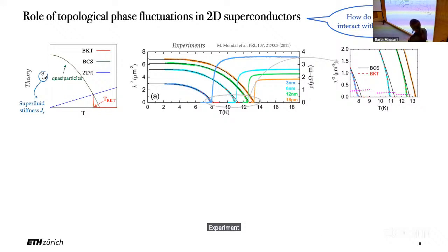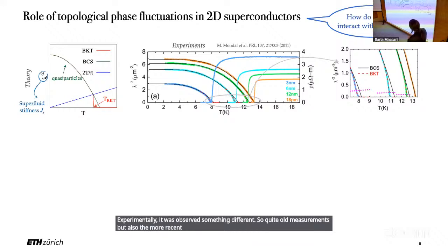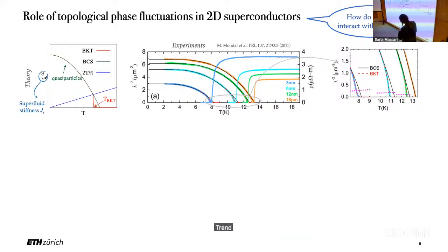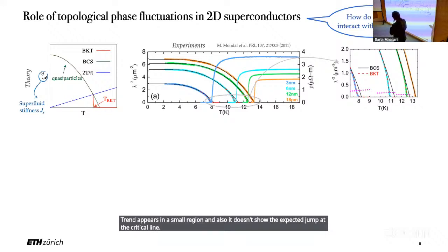Experimentally, something different was observed. These are quite old measurements, but also the more recent ones are often of this kind, taken on niobium nitride systems with different thickness. And as you can see, the deviation from the BCS trend appears in a small region, and also it doesn't show the expected jump at the critical line. It seems a more broadened transition. This was already thought to be due to the presence of disorder that produced this kind of smearing.